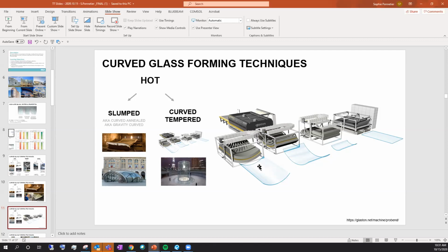So you know the orientation of your glass, the source of thermal loading. But the most important point is the detailing and making sure you allow your glass to be able to expand. And if you don't do so, or if you don't have the right capacity of the glass to sustain those stresses, this is where you have a risk of breakage.